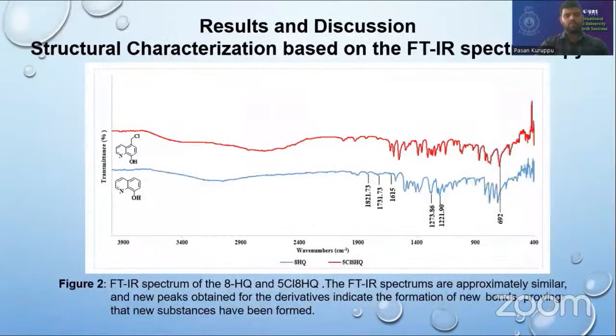So, the results and discussion. The structural characterization based on FTIR spectroscopy. The FTIR spectra obtained for both 8-hydroxyquinoline and 5-chloromethyl 8-hydroxyquinoline are shown in the graph. The blue color denotes the characteristic peaks for 8-hydroxyquinoline, while the red color denotes the FTIR spectrum for 5-chloromethyl 8-hydroxyquinoline. As we can see, both FTIR spectra are approximately similar, and the new peaks obtained for the derivative indicate the formation of new bonds, proving that new substances have been formed.